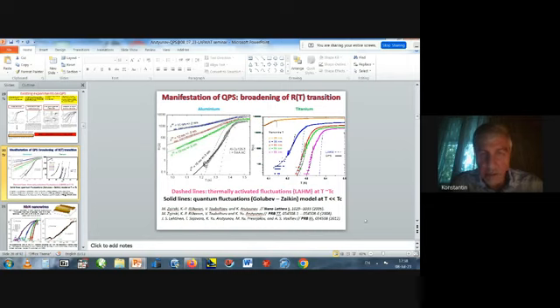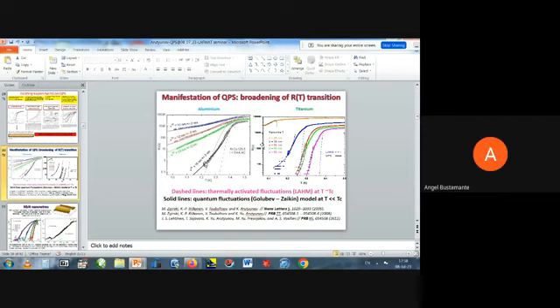So the scale here is 1, 1.1, 1.2, 1.3 Kelvin. And already we have the effect of fluctuations. So if you go to superconductors like tin or niobium, you might observe the effect at much higher temperatures. The only problem would be that then you have to go to extremely narrow nanowires, a few nanometers in cross-section. And here we work with 10, 20, 30 nanometers. That's the point. Okay, thank you very much.